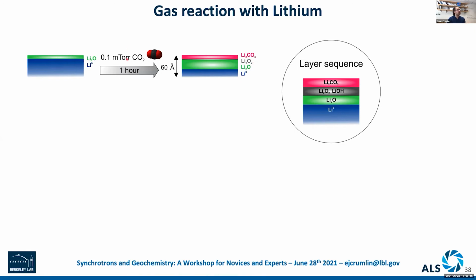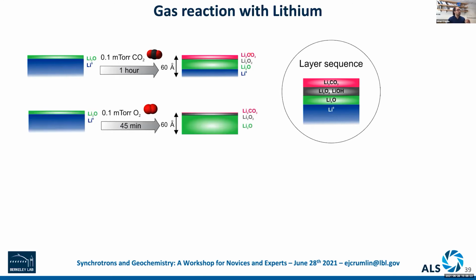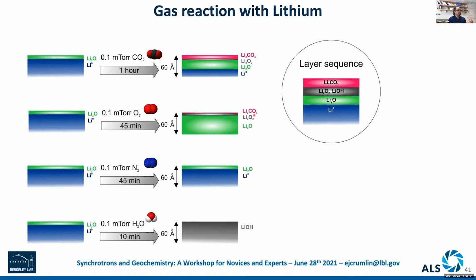So when we expose lithium to carbon dioxide, we can see the different lithium oxides, peroxides, and carbonates that are forming. We can expose it to oxygen and see again how it changes the interface during this exposure. Same with nitrogen, same with water. And so all of these different chemical species create very different interfaces on the surface.